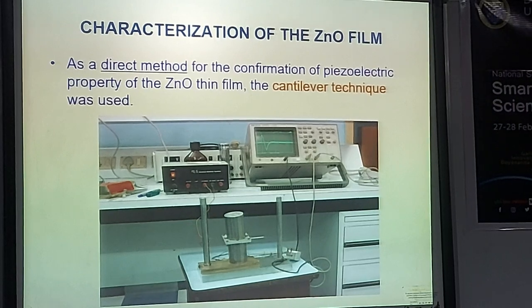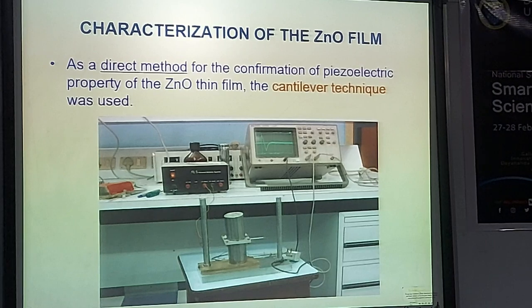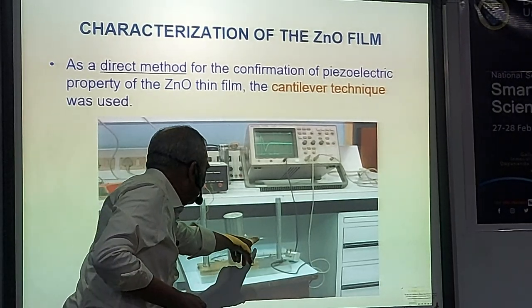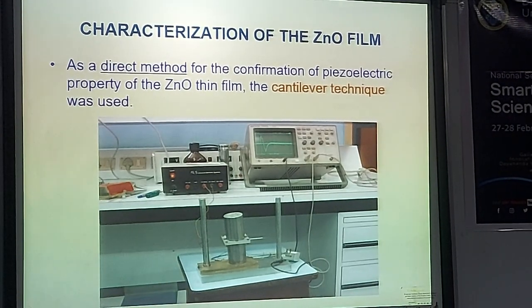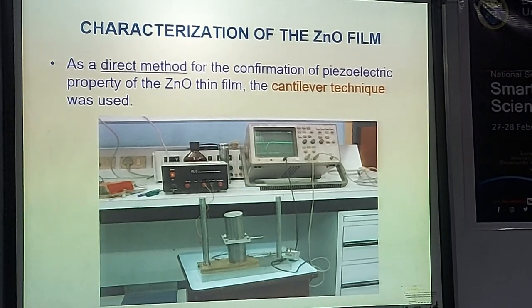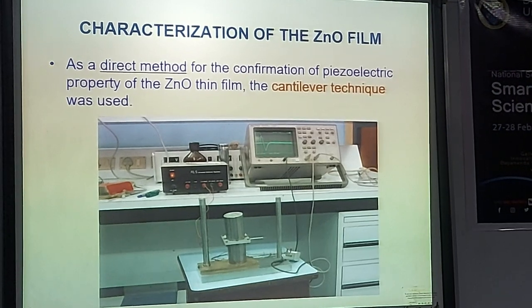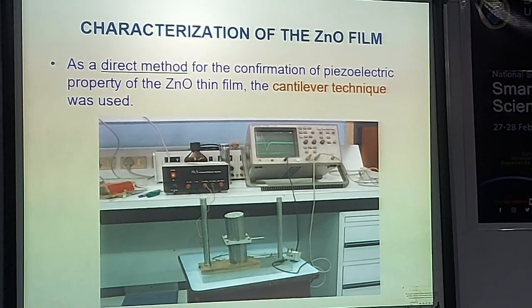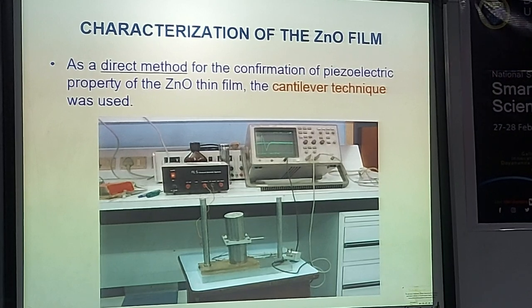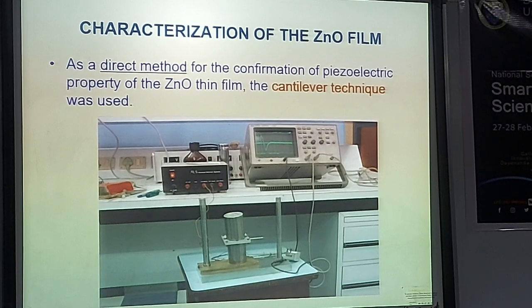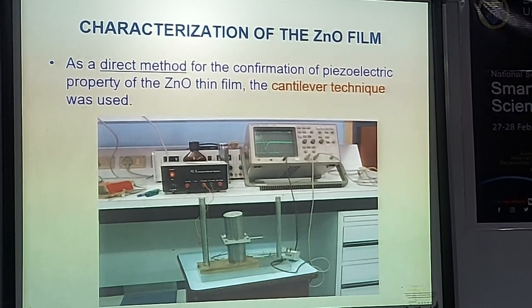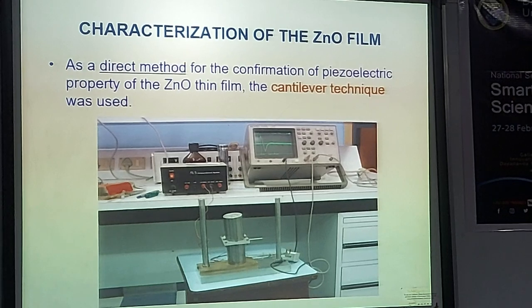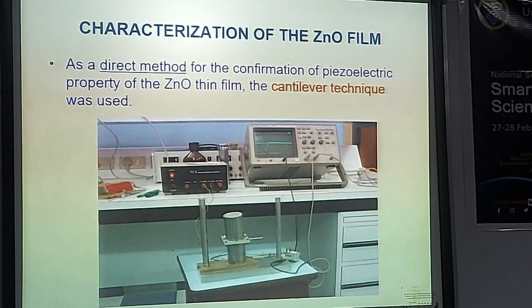This is a simple technique. What we have done is the zinc oxide film was deposited on a cantilever strip. Sorry, the pointer is not working. This is a stainless steel strip onto which we deposited the piezoelectric thin film, zinc oxide film. And on top of it, we deposited the metal electrode and leads were taken out. And this was connected to the oscilloscope. So when we subject this cantilever beam to mechanical deformation, if the deposited film is piezoelectric, it develops a charge. Charge gets converted into voltage, which can be seen on the oscilloscope. That's what it is, a simple experiment that we did.